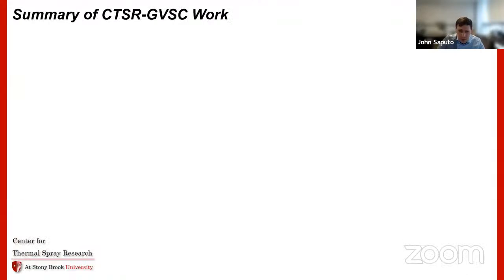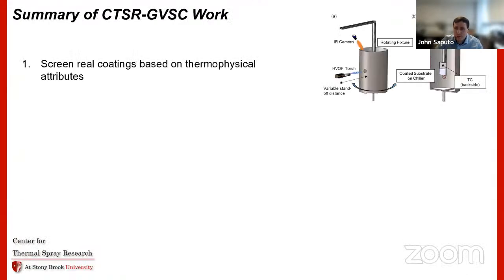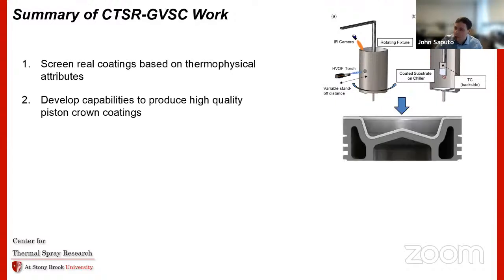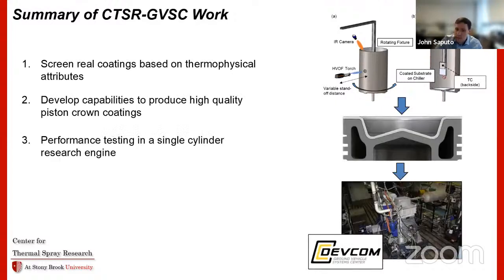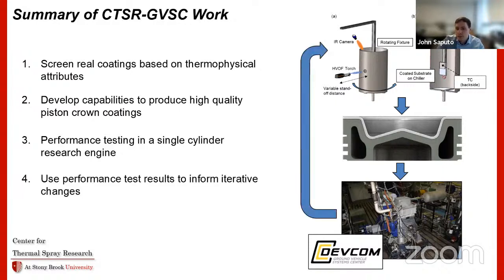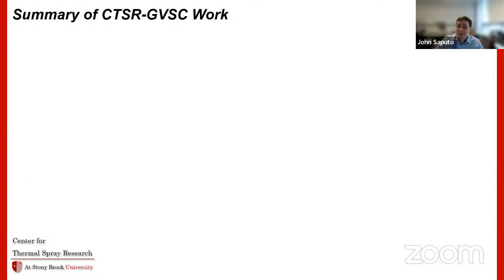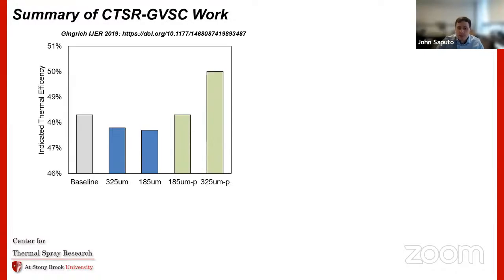So just to give you a brief summary of the work that we've done at CTSR with this, we've gone through this cycle of doing these laboratory tests, developing coatings on piston crowns, and then doing single cylinder performance engine tests, and then using that as a feedback loop to continually develop better and better coatings. So doing this, we've tested about 20 TBC varieties from coupons all the way to engine test, which is kind of interesting. So the first work that we did with this was just looking at traditional derivatives of aerospace TBCs.